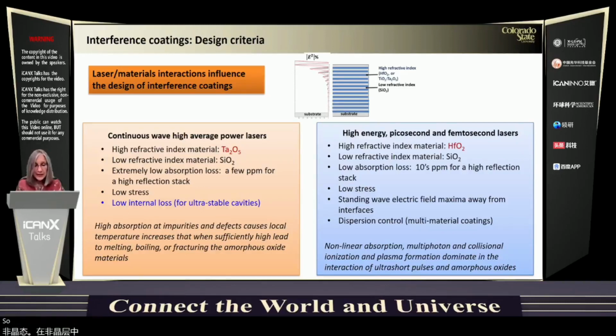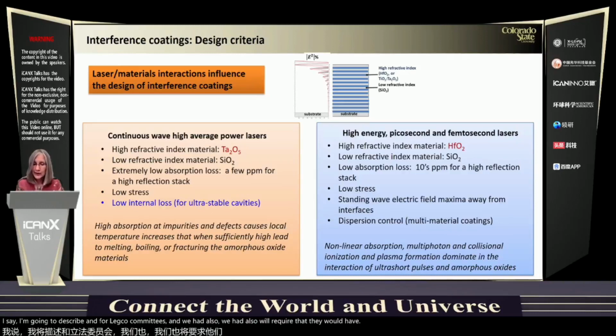So the typical material that is used as high index is tantalum pentoxide, and the low refractive index is silicon dioxide. As I am going to describe, for LIGO coatings we also require that they have low internal friction.